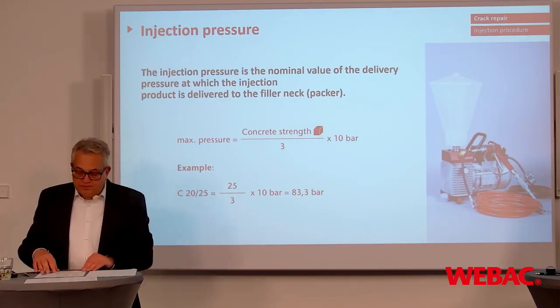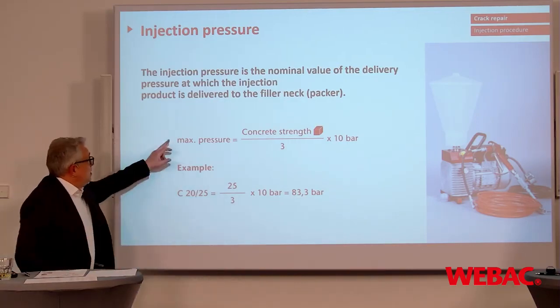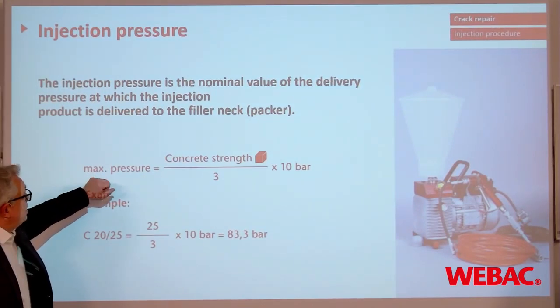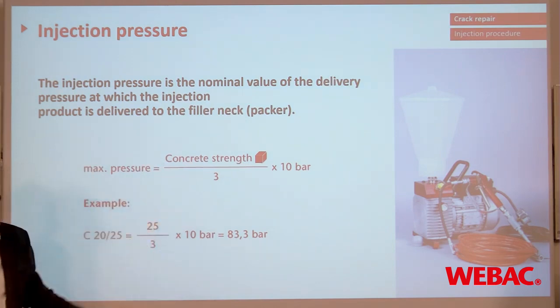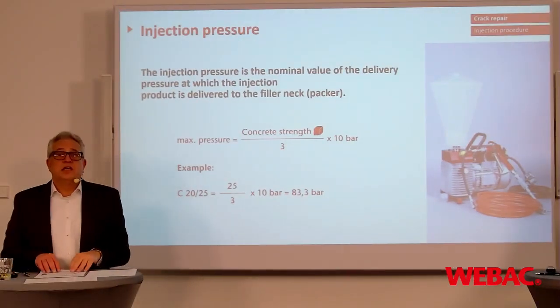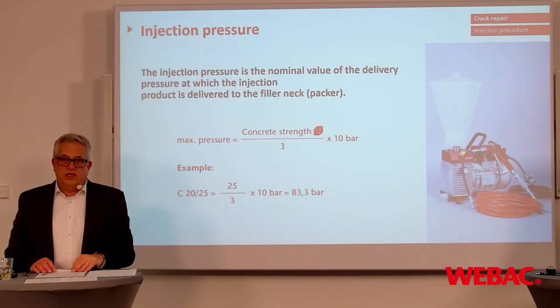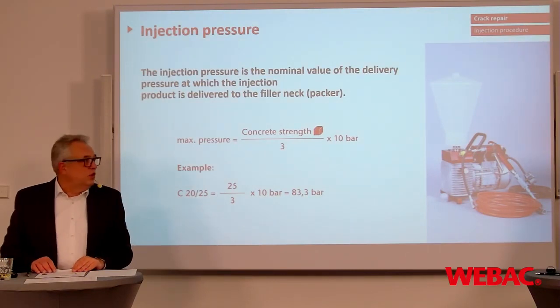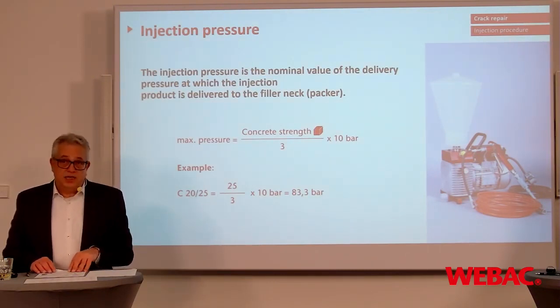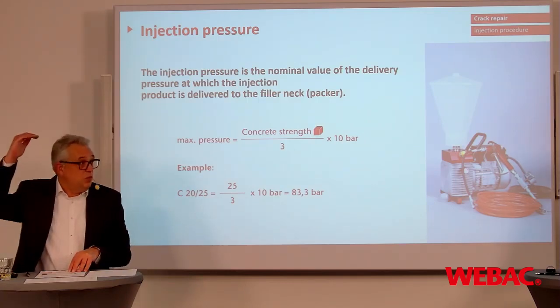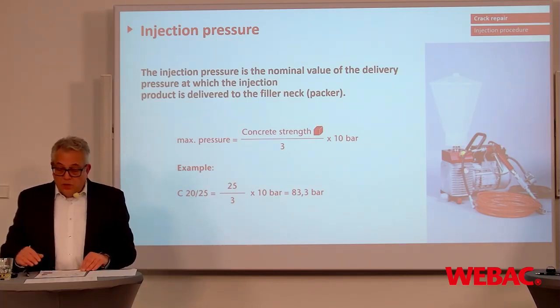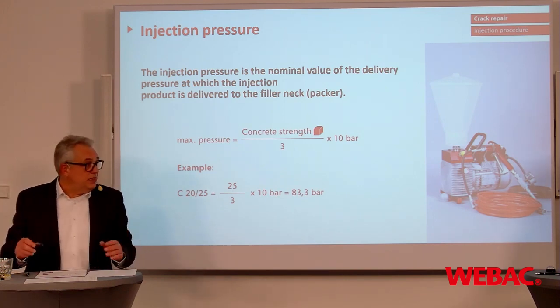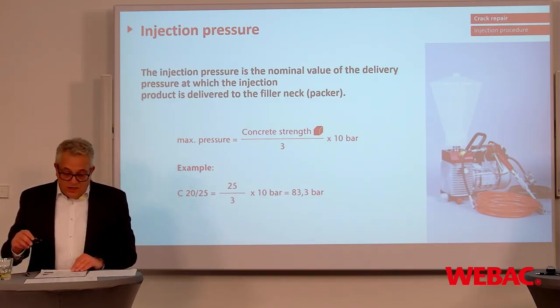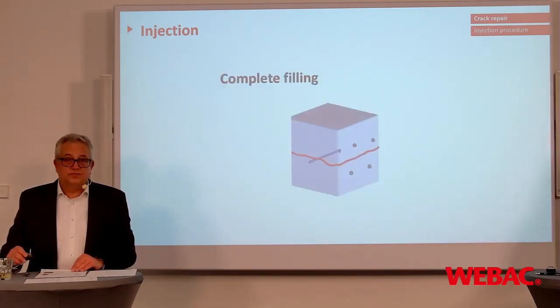A rule of thumb is to reduce the maximum pressure like following: the cube concrete strength divided by 3 times 10 bars. So for C20/25, it should be not more than 80 bars. And 80 bars are an 80-meter water column. In my world, that's a lot. Again, this is general speaking. It depends on the case and on the building site.